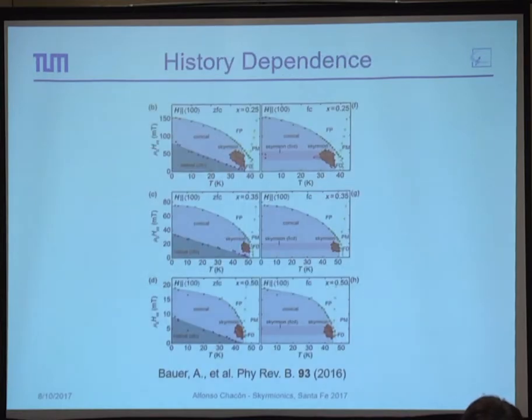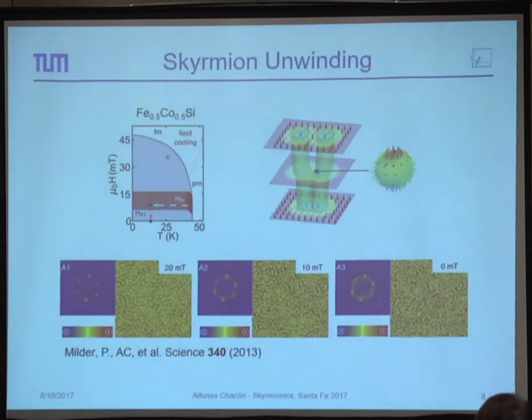That was important for us because allowing us to metastably take the Skyrmion lattice down to the lowest temperature, regardless of the doping, gave us the possibility to perform the first magnetic force microscopy measurements on this compound.